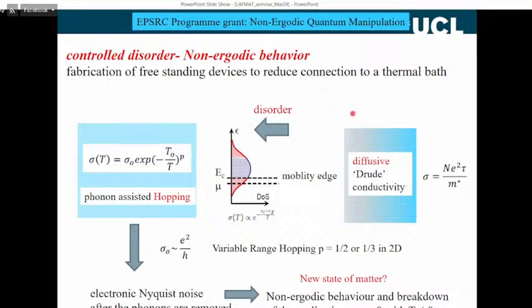And if it was disordered, it would go from a diffusive conductivity region. So when the transport is not disordered, it's so-called diffusive, and charge diffuses through the system. We describe the conductivity as n e squared tau over m star, where n is the carrier density, tau is the elastic time constant or effective scattering time, and m star is the effective mass.